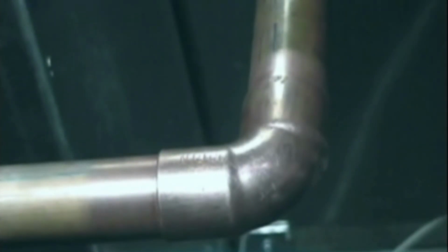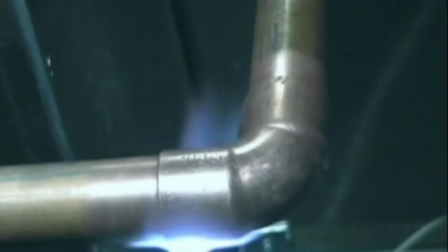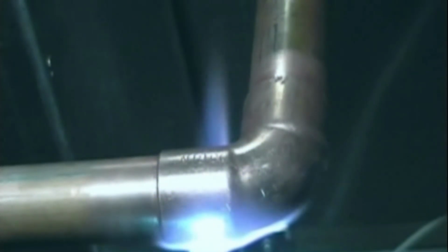This oxidation layer is essentially a chemical force field. A force field. And the solder can't penetrate that field. Solder physically cannot bond to an oxide. At all. Not at all. A solder joint is not like hot glue sitting on top of cardboard. It is an intermetallic bond. The liquid tin in the solder must physically dissolve a microscopic layer of the solid copper to form a new hybridized metal alloy at the boundary layer. Wow, so they literally merge into a new metal.